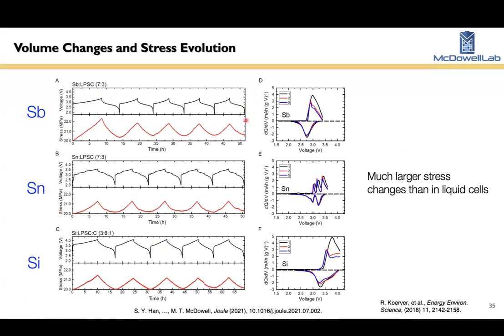These are electrochemical plots on the top in black where we're charging and discharging various cells. And then the red down here is real-time measurements of stress changes, stack pressure changes in these cells with a force sensor. What you see is as you charge and discharge the battery, there's a big increase by a few megapascals of the stress in the cell and then a decrease of the stress. In general, these changes in stress are higher than in liquid cells because there's a more confined environment in these solid-state batteries. There's a really good paper here from Jürgen Janek's group that goes into some details about how the partial molar volume of lithium influences the stress evolution, and it is highly recommended.